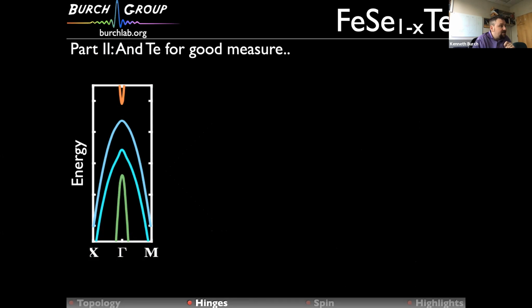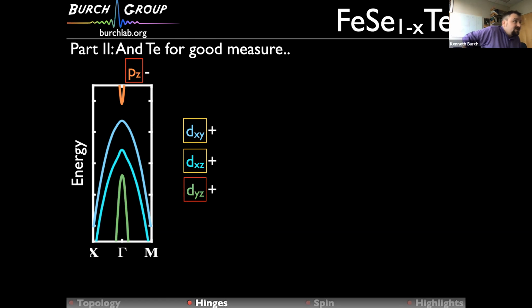So they said, look, my conduction band is essentially near gamma, is essentially this pz orbital coming from the chalcogenide. And I've circled it in red to just say that it's of a certain representation, and I put the minus sign to indicate that it's odd under inversion. Then they noted that of course, near gamma, there are 3 d states, so dxy, dxz. They're both even under inversion, and they're of a different representation than the p orbital. And then finally, there's dyz, which has the same representation, but is also even under inversion.